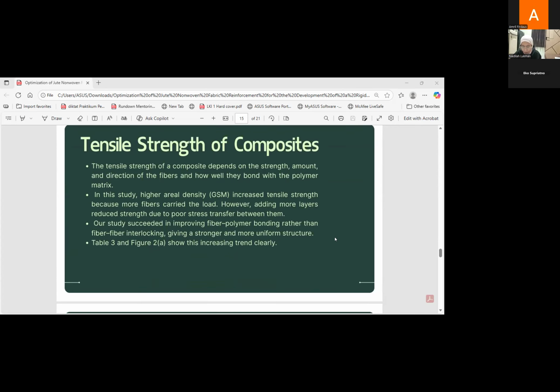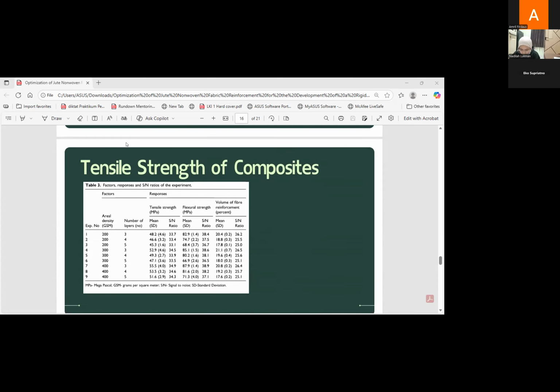And I want to explain the evaluation of tensile strength of the composite. The tensile strength of the composite depends on the strength, amount, and direction of the fiber, and how well they bond with the polymer matrix. In this study, higher areal density increased tensile strength because more fiber carried the load. However, adding more layers reduced strength due to poor stress transfer between them. And our study succeeded in improving fiber polymer bonding, the fiber interlocking gives a stronger and more uniform structure.